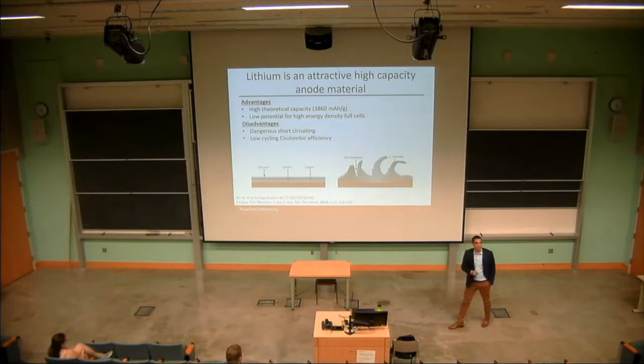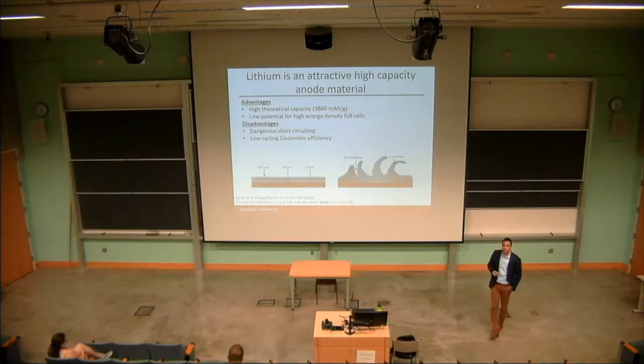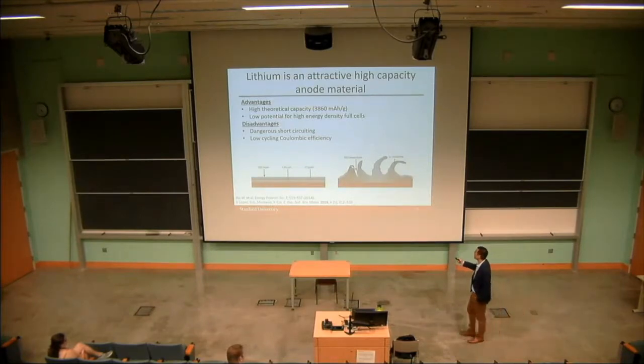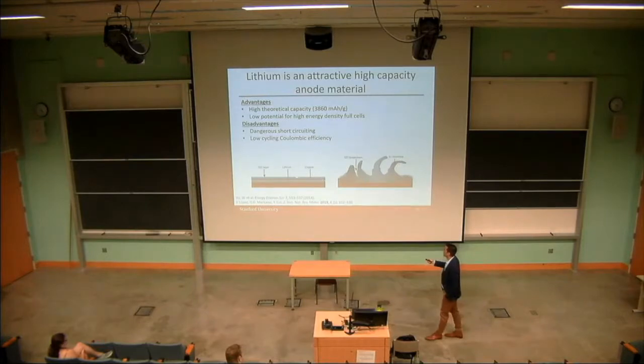Unfortunately, reality is rarely perfect, and so what we actually see is the solid electrolyte interphase, or SEI, breaks down, and the lithium grows through it, and so you have these very inhomogeneous structures that form. They can be moss-like, they can be dendritic, they can be rod-like. There's, depending on the chemistry, a lot of different structures that can form. And then these dendrites can eventually grow through your cell and cause those dangerous short circuits I mentioned earlier. So we want to avoid this sort of structure and really promote as dense of a lithium deposit as we